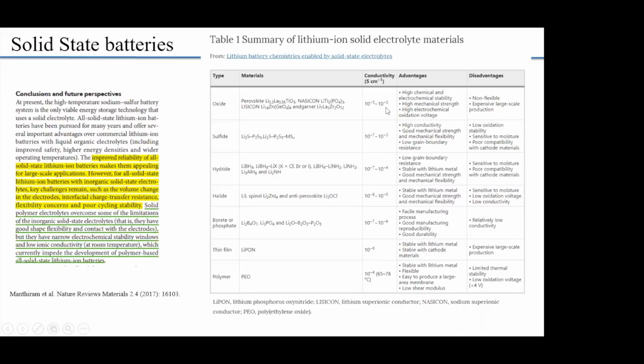They share this table where they highlight the advantages and disadvantages of each one. Previously we showed a big picture, a collage that talked about oxides, sulfides, hydrides, halides, thin film, polymer, all of that. For each one of them, they highlight the advantage and the disadvantage. For example, the polymer is flexible, stable with lithium metal, and easy to produce. Polymers have been around for many years and people know how to make them, but they have limited thermal stability and low oxidation voltage. Some of the sulfides have low oxidation stability, are sensitive to moisture, and have poor compatibility, and many of them have cycling problems. For example, they may not sustain thousands of cycles, and cost has not been considered. Some of these materials can be pretty expensive to make at large scale.